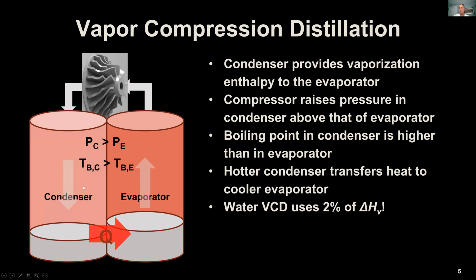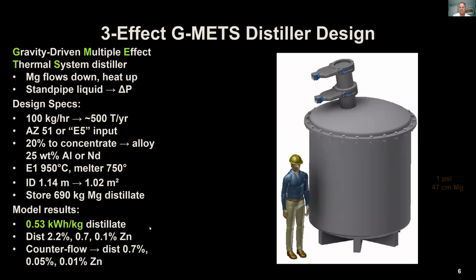So the hotter condenser transfers heat to the cooler evaporator. This is so efficient that water vapor compression distillation can take as little as just 2% of the enthalpy of vaporization as input energy, with the other 98% coming from the condenser. That's for low salt water, not for seawater. So this is what we came up with.